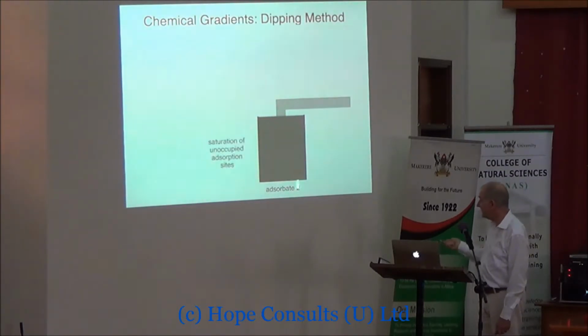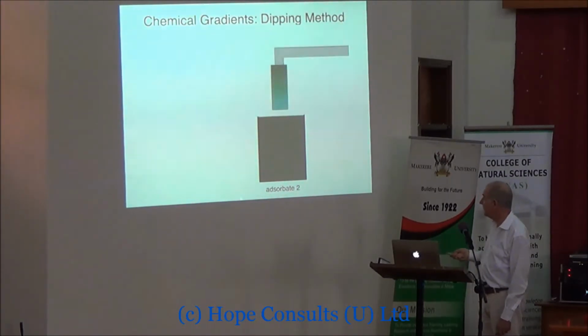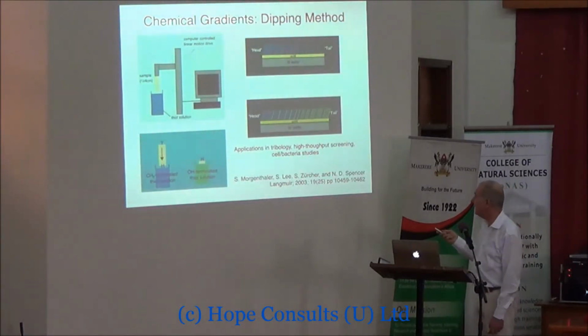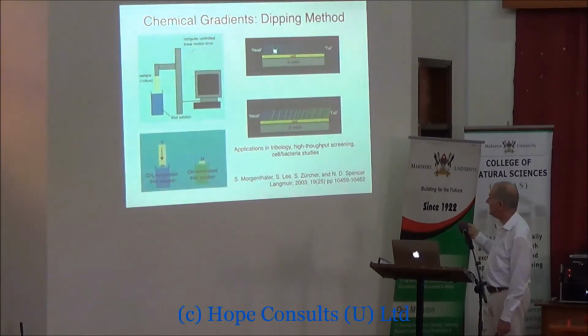And then you just immerse it quickly into the second adsorbate, and now you're doing a gradient. At this end, you've got the first component in high concentration. At this end, you've got the second component. Just to show you what I did in a diagram, this was the first dip where we had a high concentration at this end and a low concentration at this end. And then you plunge it into the second component, and you fill in all the gaps that you have here with the second component. And now you have a gradient in surface chemistry from one end to the other.